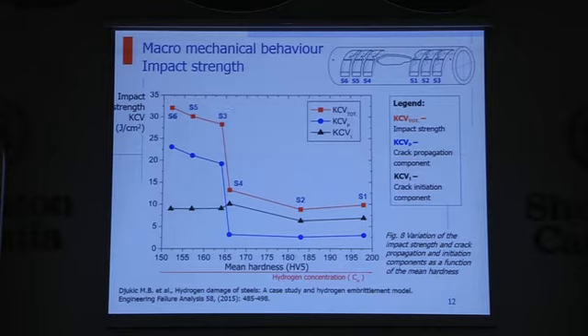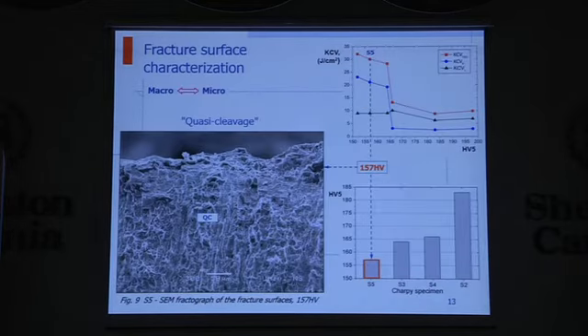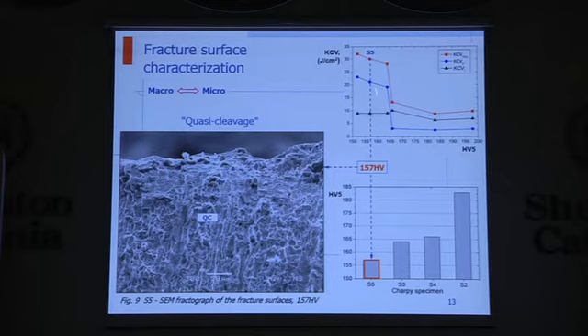We will also investigate the fracture features of these specimens. S4 and S5 are relatively good — they have good values — but we can observe quasi-cleavage fracture features, which is pretty well defined. Under larger scale, we can see that the fracture picture consists of areas of transgranular fracture and micro-void coalescence patches, with corresponding values of impact strength, hardness of the specimen, and porosity with micro-voids.